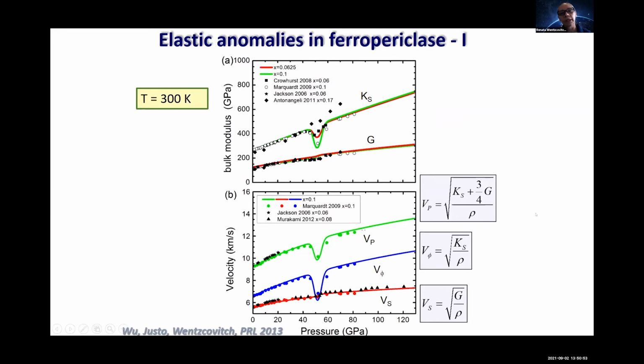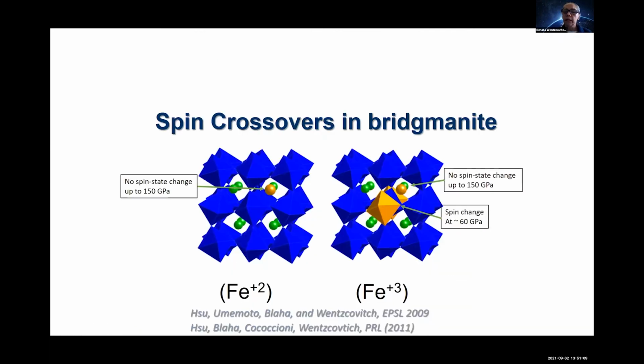But this is what we really needed to address the mantle more carefully here. Brillouin scattering and ab initio quasi-harmonic thermoelasticity agree pretty well in predictions at 300 Kelvin. The same thing happens, of course. To understand the mantle, we still need to understand spin transition in the main system, bridgmanite. There is no spin transition in ferrous iron in bridgmanite. There is a spin transition in ferric iron in the octahedral site, and it's at a slightly higher pressure, but qualitatively the effect is the same.